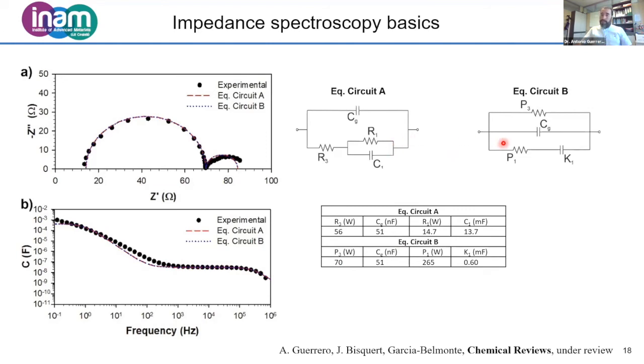Well, both fittings are not equally valid, because from these fittings, we will get useful information from our devices. For example, we can get the geometrical capacitance of the device in the high frequency region, or we can get the resistance related to, let's say, recombination of carriers or electropolarization. But there are different factors that we can measure. Here, once we do the fitting, we can see that the geometrical capacitance in this case is exactly the same for the two equivalent circuits, but all the other parameters are totally different, and they have different physical meaning. So it's very important that we use a validated equivalent circuit and we understand the meaning of each of the elements of the equivalent circuit.